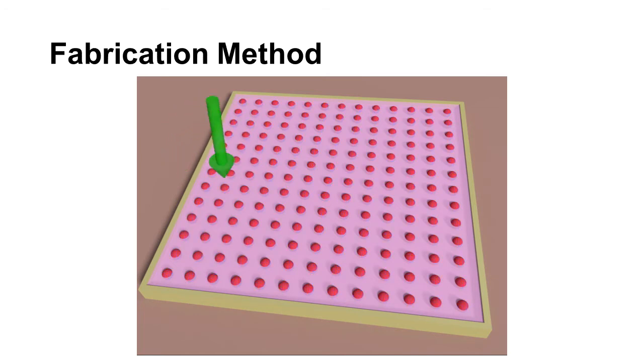Here, we generate a magnetic flux density of 100 mT, denoted by the green arrow. We first apply a magnetic field to the right. When the particles are aligned, we shine UV light on the left half of the polymer, which is our first curing region. This initiates local polymerization and freezes magnetic particles within it.